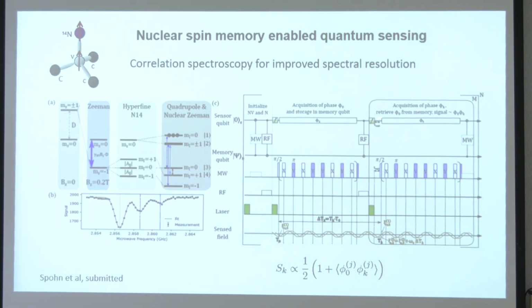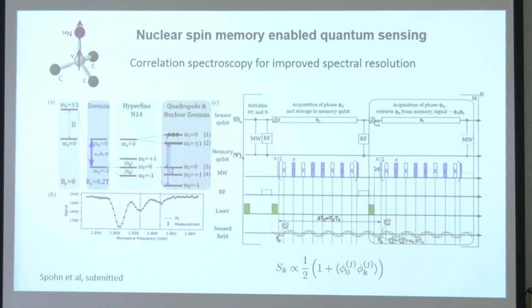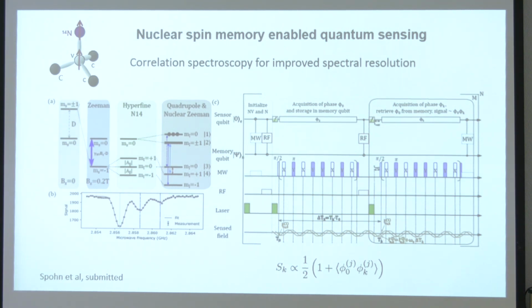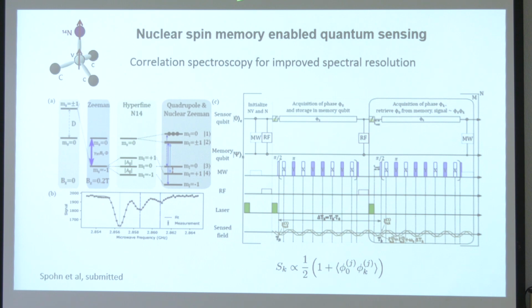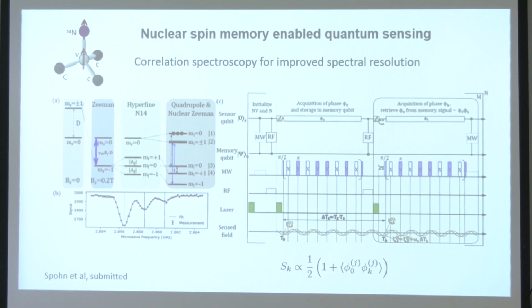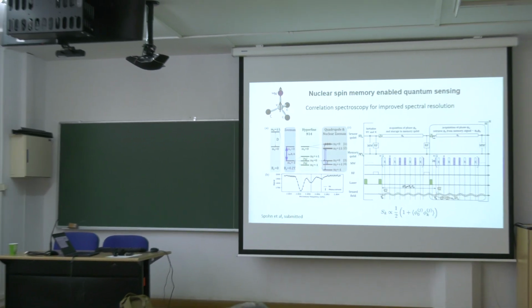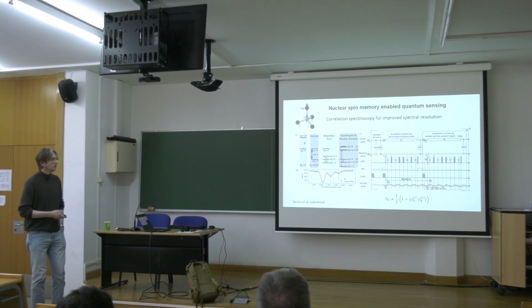And during the train of measurements, at the very end of the measurement, we measure the state of the electron spin and add the phase that was initially stored in the nuclear spin. With this, we can measure the correlations between the phase acquired in the initial period and the phases acquired during the next period of time. It looks a bit complicated, but it's now tracking the correlation of the external signal over a long time, which is limited by the coherence time of the nuclear spin, which is now longer. So now you can improve your resolving power.